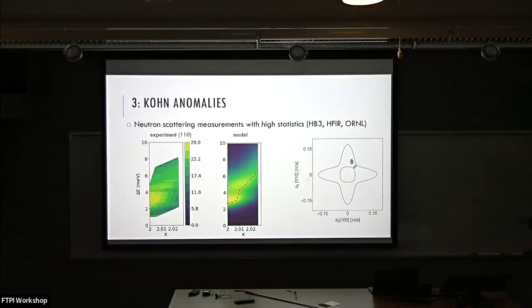So there's an interband here. This is very low Q, so it's a bit hard to do the measurements. But there seems to be something happening. This is now a dispersion measurement very close to the zone center. And of course, this resolution ellipsoid integrates over a lot of stuff. But you can still see some funny things here. There's a bit of a gap here. That's the most obvious thing.